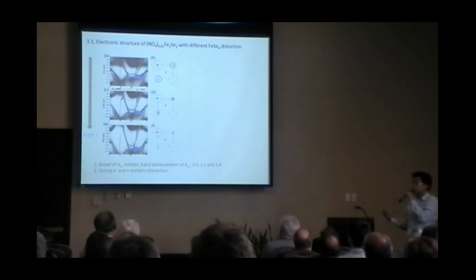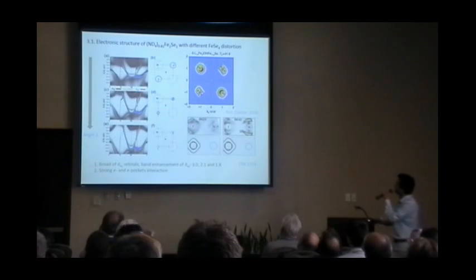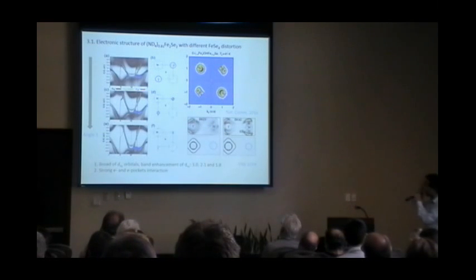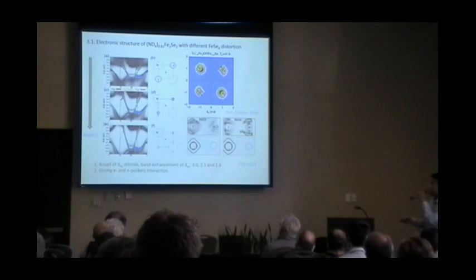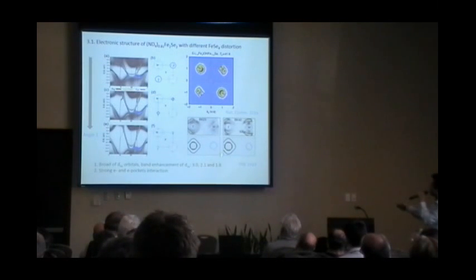Another thing that we found is the Fermi surface change. From B to F, we found a very important thing about the pockets from the M points. This interaction may be important. Actually, we found there is a new paper. They already measured the real Fermi surface of the 1-1 compound. We found a very close Fermi surface compared to our calculation. This Fermi surface change contrasts with those of the iron pnictides. In the iron pnictides, the interaction between the gamma and the M is very strong, even the TC is very high.